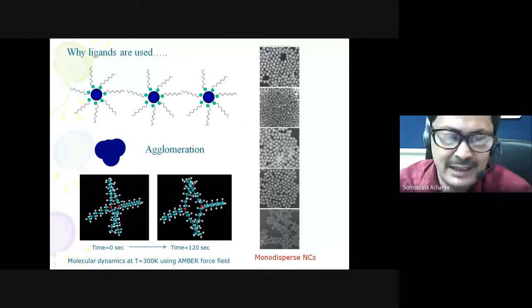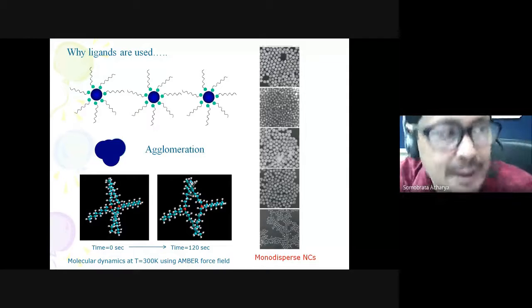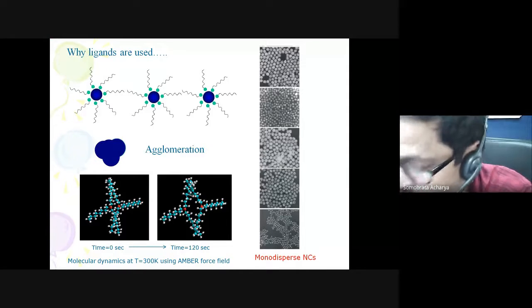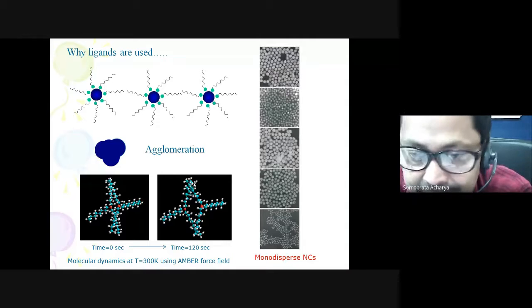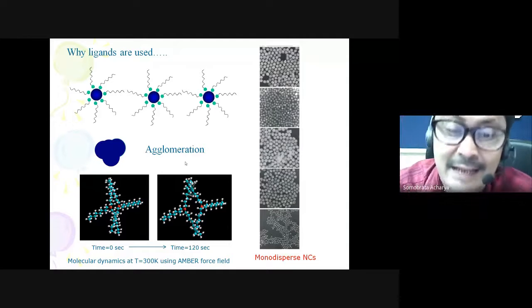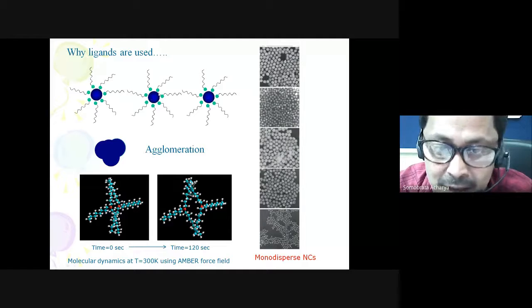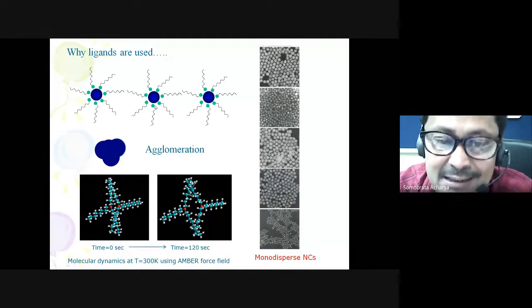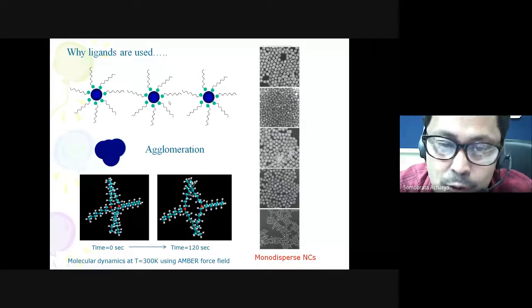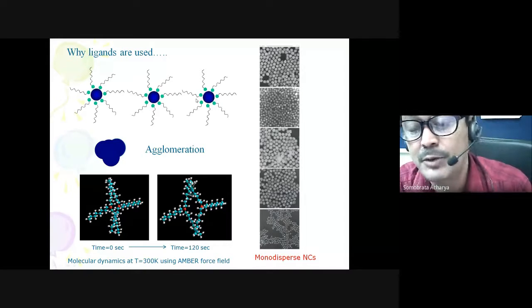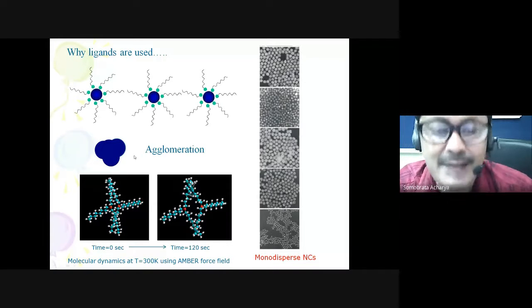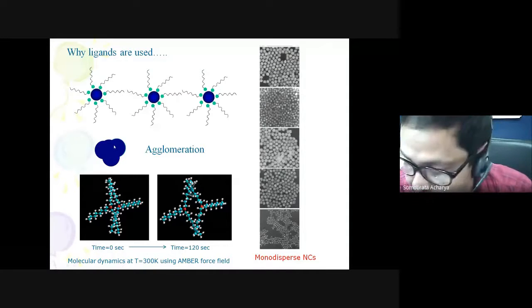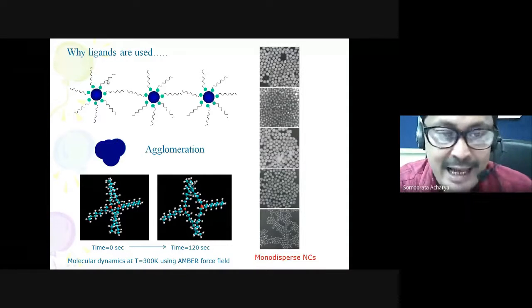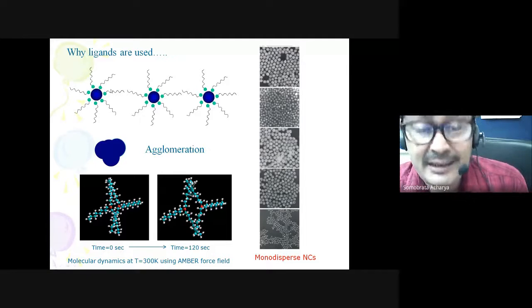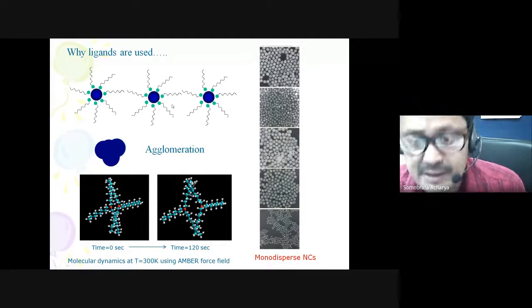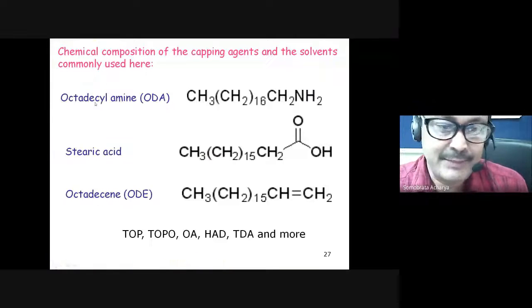Now, one thing is very important here: if you want to have a very good distribution of these nanocrystals, you must use the ligand. If you won't use the ligands, these are the nanocrystals there. If you won't have this kind of ligands, which are organic molecules, then these two nanocrystals will come closer and will form an aggregated structure. Once you have this aggregated structure, you cannot control the shape or sizes. So ligands are a must in the solvothermal synthesis of nanocrystals. Okay, so these are the typical types of ligands.